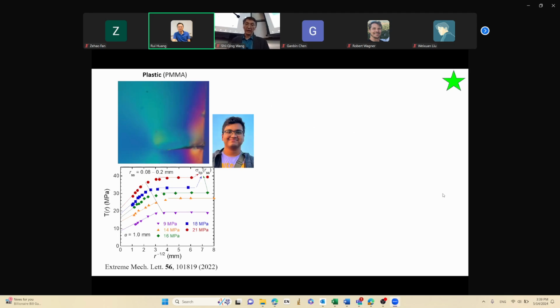So here is the case of PMMA. We had a crack, and we do birefringence, and we see the butterfly. We try to analyze what the birefringence teaches about what's going on at the tip. And we find that the birefringence levels off as you approach the tip, which is to the right because I plotted it as 1 over r to the minus 1/2. And it has a comfortable zone. It levels off about 100 microns away from the tip.